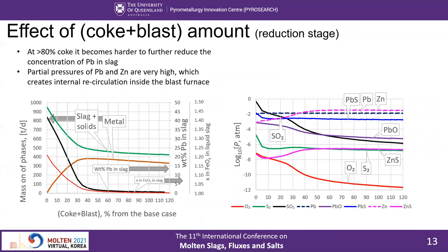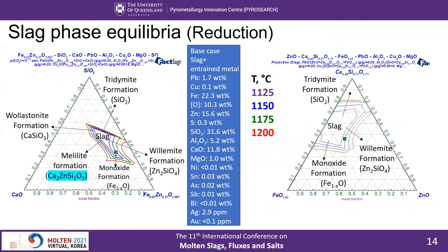The sensitivity analysis shows the effect of coke plus blast amount. The main conclusions are that reduction of PbO in slag requires increasingly more coke at lower blast amounts. Partial pressures of lead and zinc are very high, so gas needs to be treated to bring them back into the furnace. In the blast furnace, they recondense when in contact with feed from the top. Channeling and high temperatures at the top of the furnace result in higher concentrations of Pb and zinc escaping into off-gas. The matte phase does not form in this series of calculations since the temperature is high and significant copper has been removed at the smelting stage.